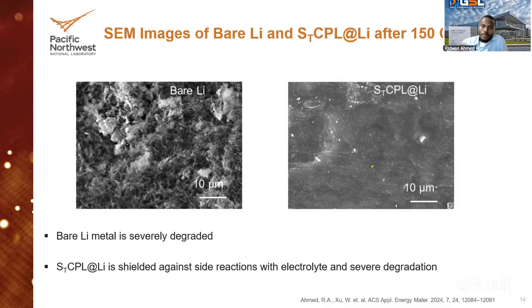But if you look at the protected lithium, we can still see that protection layer on top of the lithium. So the lithium is beneath and you have the protection layer. So that shows that it's still protecting it from reacting with the electrolyte. So that's one of our contributions in terms of trying to improve the stability of lithium metal batteries.